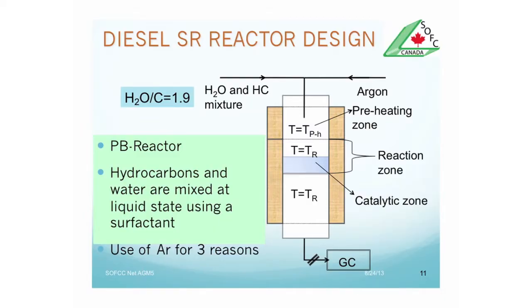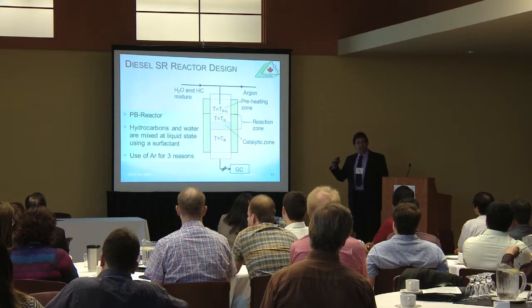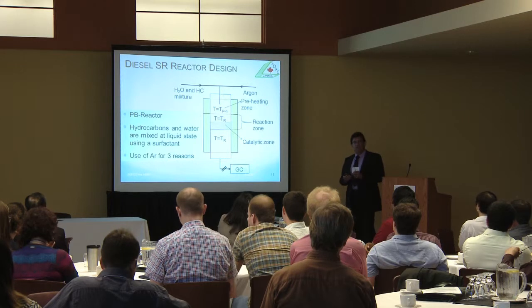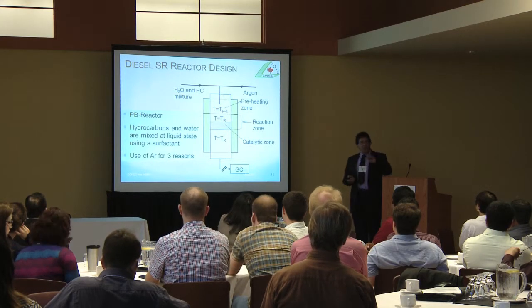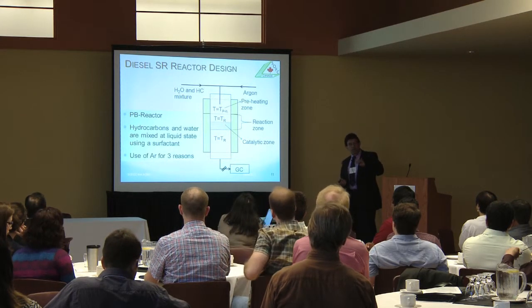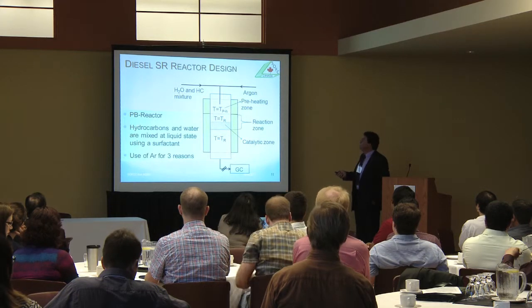Hydrocarbons and water are mixed in the liquid state using a surfactant at the appropriate ratio. And we have used argon for 3 reasons: as an energy provider to disperse the liquid phase, as an internal standard for the analysis, but at the same time as a means of controlling the gas hourly space velocity.